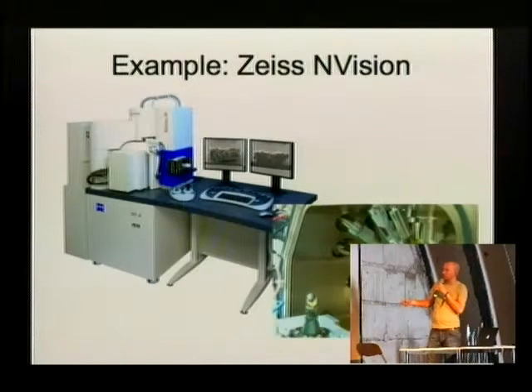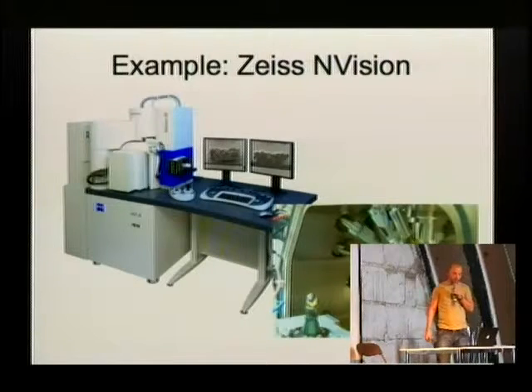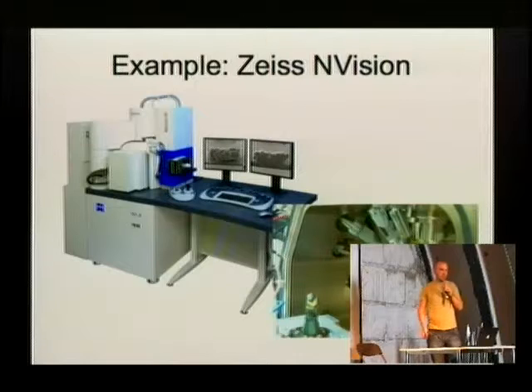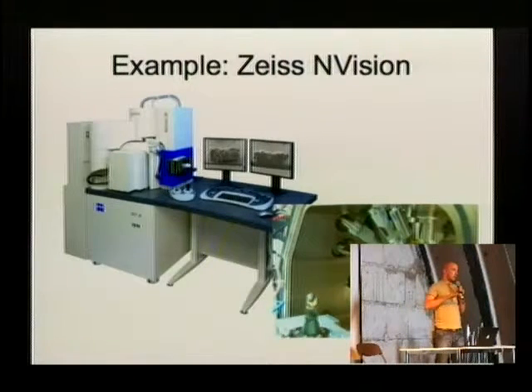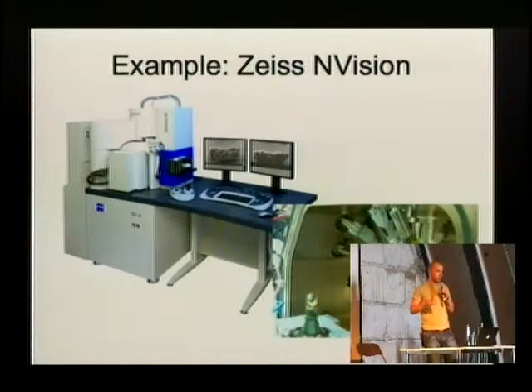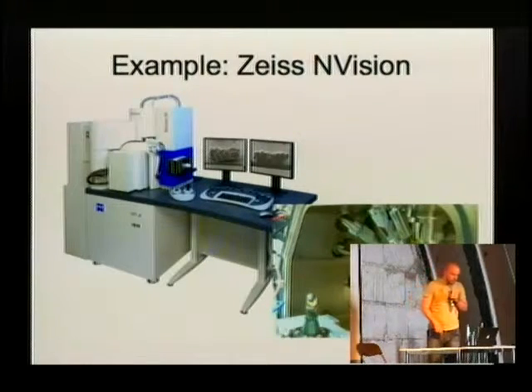Here is a close-up of the chamber of the microscope. Here in the middle you see the electron beam coming in. From this side, actually from behind, comes the ion beam, and you can mount your sample in a region where the ion beam and the electron beam cross. That gives you the possibility to use the ion beam to change the surface of the sample while you are watching the whole thing with the electron microscope.